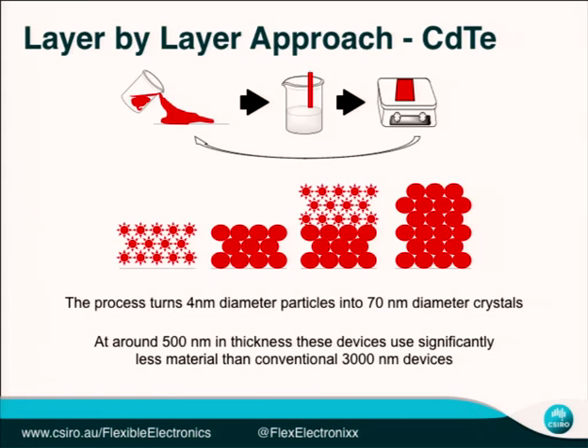Now, what's going on inside these particular devices is that they made these nanoparticles, and in this case, these were cadmium telluride. Shown over here is the cadmium telluride nanoparticles with some ligands around the outside to make them soluble. They then put them through a very quick chemical and thermal treatment, and those particles start to grow a little bit bigger. Then we put another layer down on top and do a little chemical and thermal treatment, and then they grow a little bit bigger. Now, by doing this layer by layer approach, we stop cracking or the films developing defects. And the end result is that we've taken our 4 nanometer nanoparticles at the start and turned them into 70 nanometer crystals. At that size, those crystals have about the same properties as the bulk semiconductor.